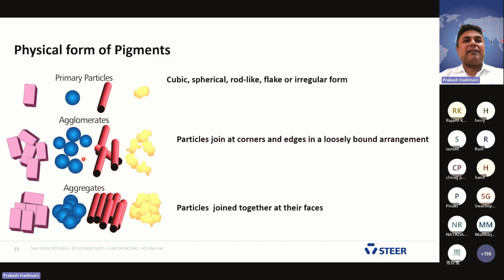Agglomerated particles are easy to disperse because some of the pigments are not hygroscopic in nature, while some of them are highly hygroscopic in nature. And if heat and moisture come into play, the pigments tend to agglomerate. The particles joined at corners and edges are a loosely bound arrangement, so it's easy to disperse. In the case of aggregates, the particles are joined together on the surface. Each pigment is completely bound together on the surface, so it's difficult to disperse and difficult to reduce in size. We need to apply more energy to break these aggregates. This is the only difference between agglomerates and aggregates in the pigment.